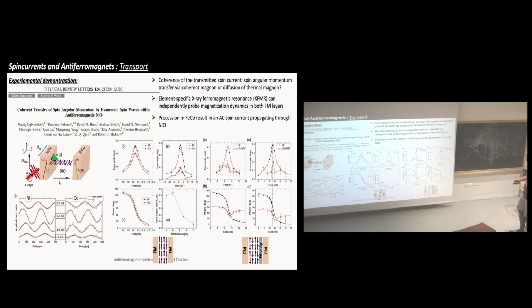So what they've done is add either a silver or a palladium layer in between, and they can still see something happening. So that means that the spin currents which are arriving here can go through silver easily, because it also has a long spin lifetime, and then enter the second ferromagnet.